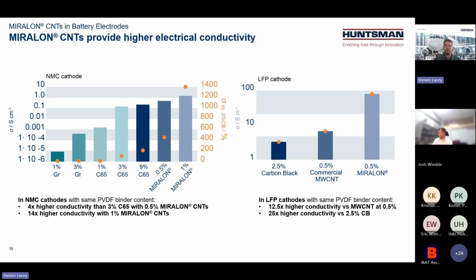On the LFP cathode, also with the same binder content, you can see that when we compare ourselves directly to carbon black, using 1/5 of the material, we have 25 times higher electrode conductivity. While when we compare to a very industrial multi-walled CNT on the market, we also see more than an order of magnitude higher conductivity at the same loading of 0.5%.